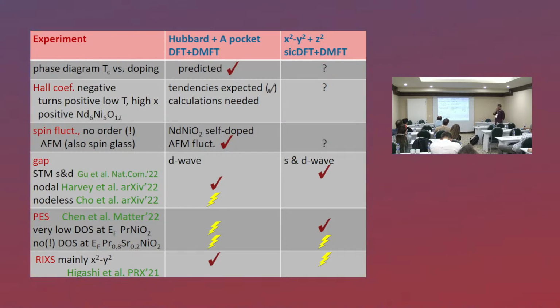Then we get antiferromagnetic spin fluctuations, and well, Ariando will tell us maybe more about different kinds of spin fluctuation. There's also spin glass behavior. You also have some ferromagnetism seen in the system. So our point of view is that this spin glass and ferromagnetism is due to disorder in the system, excess hydrogen or oxygen, but antiferromagnetism has been firmly established in many experiments indeed. The self-doping of the nickel band nicely explains why it's only fluctuations and not long-range order.